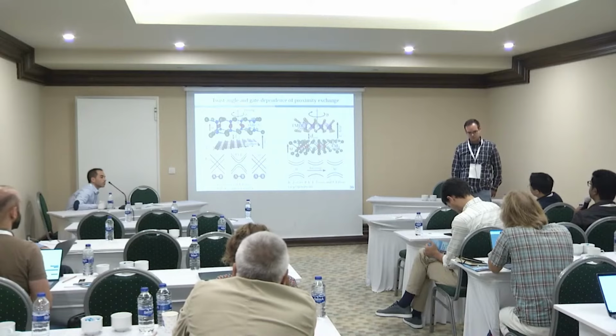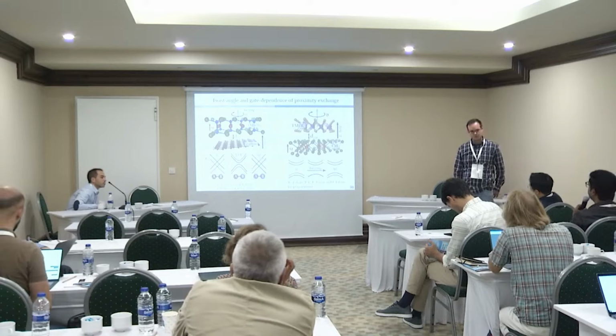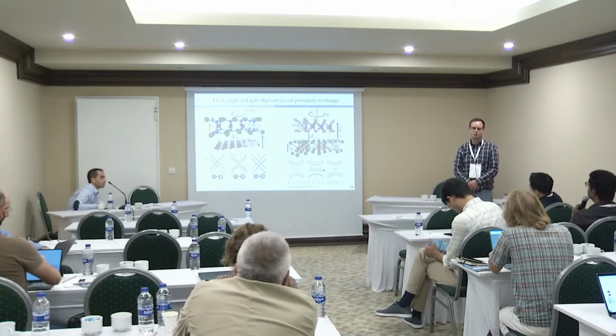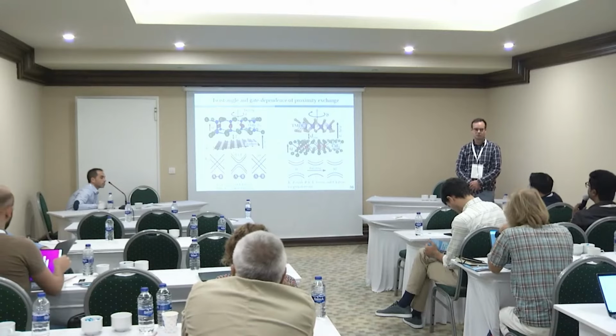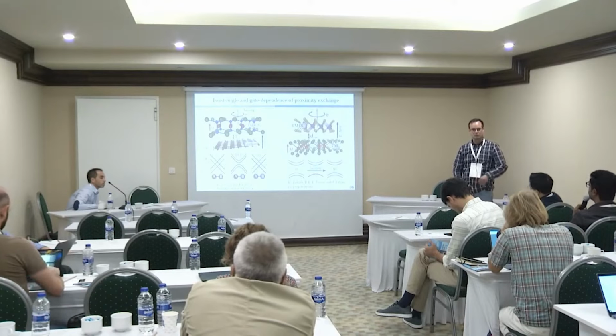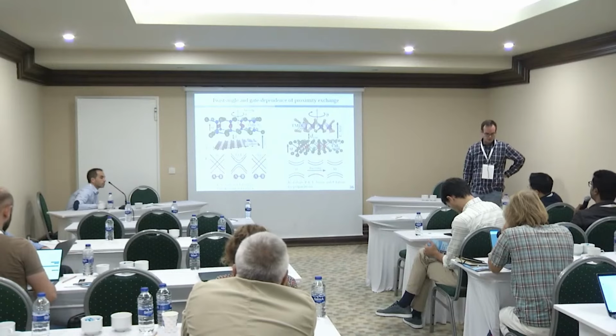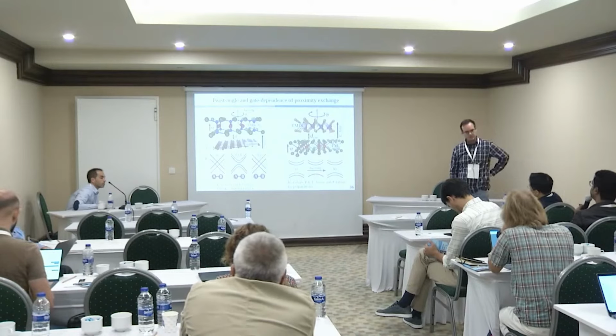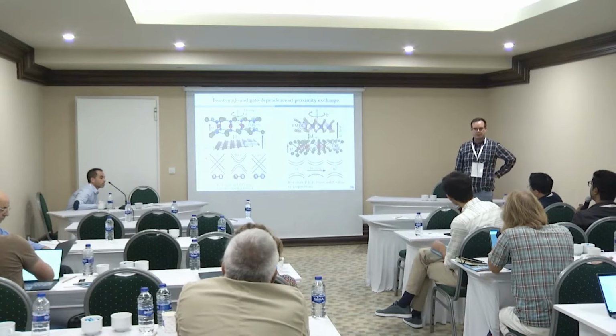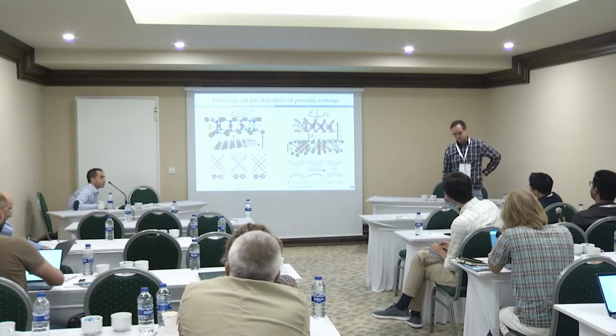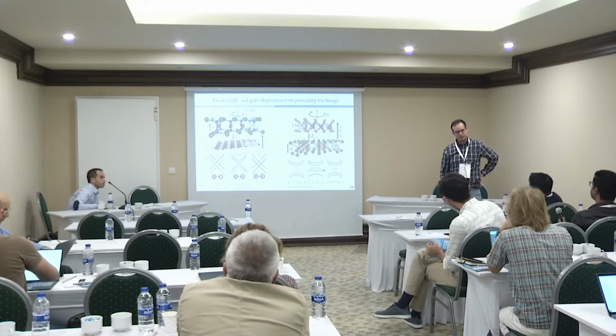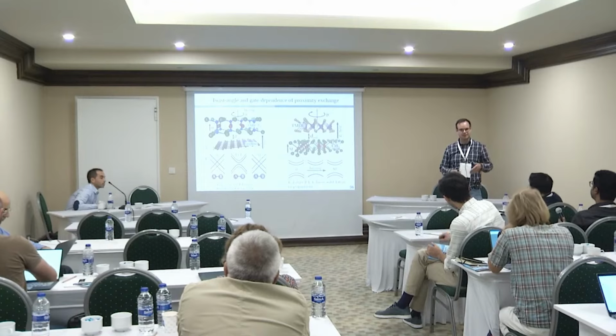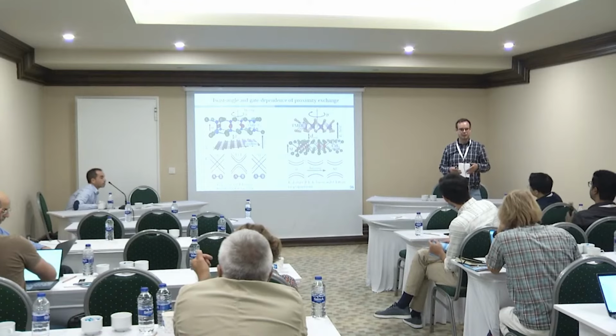Because for bilayer graphene, we can understand that the bottom layer is in close proximity to the WSe2. That can enhance the spin orbit coupling for the bottom layer. But for the top layer, since there is a van der Waals distance between the top and bottom layer, the overall spin orbit coupling is small. So my question is, what will happen for monolayer graphene? Can it act similarly to bilayer graphene, where we can switch the proximity induced spin orbit coupling with a perpendicular field? Or is there a small impact of the proximity spin orbit coupling upon electric field, but you cannot switch it, because the bilayer structure is completely different?